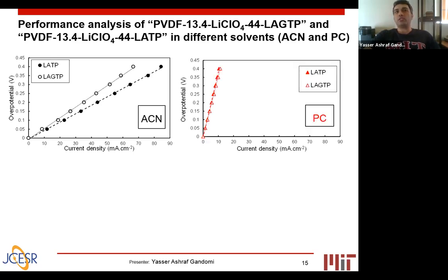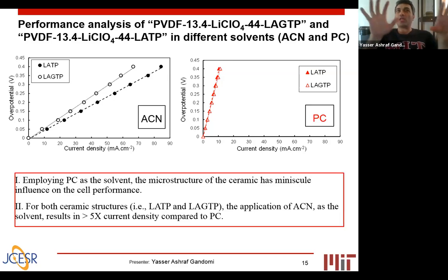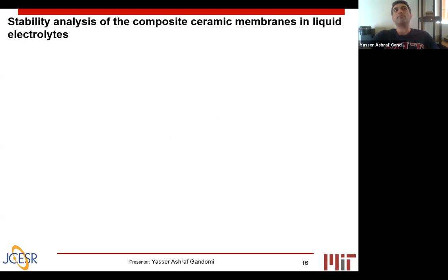The next step was to analyze the performance with other ceramic structures. We ran similar experiments with acetonitrile and PC, and comparing them side by side, it's very clear that the ceramic structures contribute to the performance when we use highly conductive solvents like acetonitrile. But when we use PC, the ceramic structure does not contribute to the improved performance. And regardless of the structures, we could achieve almost 5 times higher performance with acetonitrile compared to the propylene carbonate.